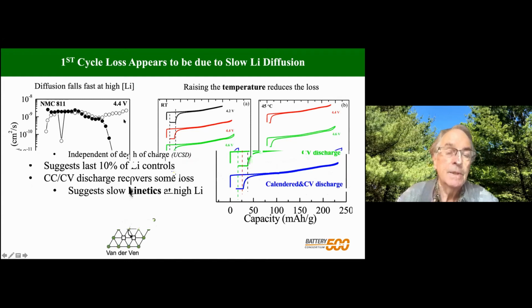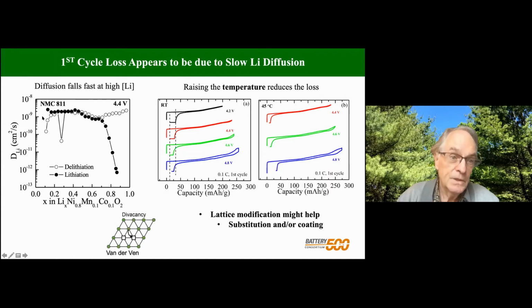You'll see that this is not really an issue on charging, except maybe the last 5 or 10%. So these materials are very fast chargers, but not so fast discharges. So this is again saying diffusion is limiting it. On the right-hand side here, I'm showing you the effect of charging to different voltages. And you can see, obviously, the higher the voltage we go, the more capacity we get.